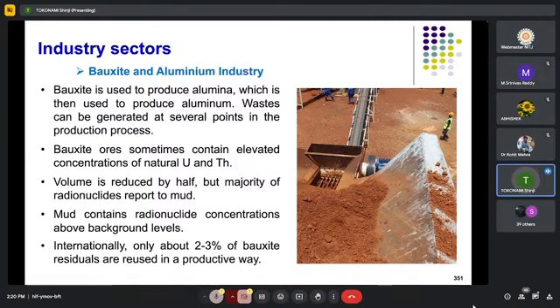Bauxite and aluminum industry. Bauxite is used to produce alumina, which is then used to produce aluminum. Waste can be generated at several points in the production process. Bauxite ores sometimes contain elevated concentrations of natural uranium and thorium. Volume is reduced by half, but the majority of radionuclides report to the mud. Mud contains radionuclide concentrations above background levels. Internationally, only about 2 to 3% of bauxite residues are reused in a productive way.